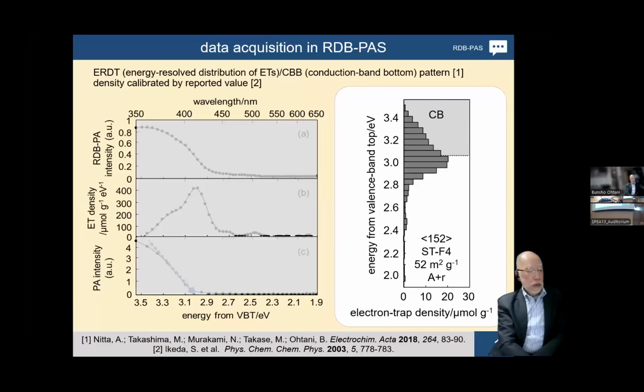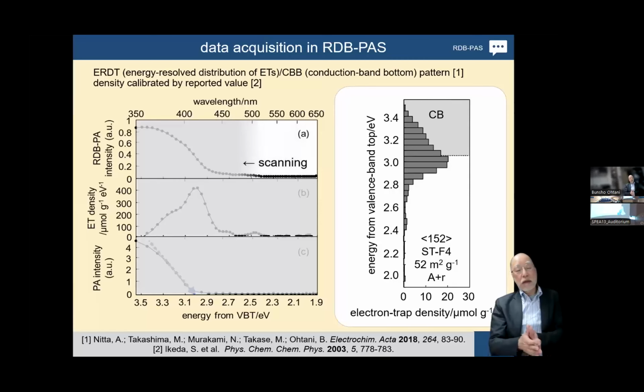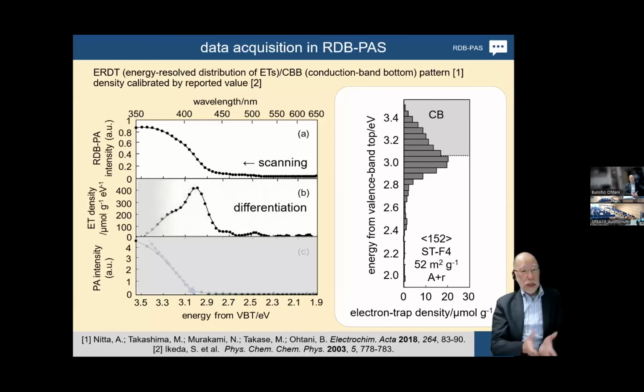The left top one is the scanning of excitation wavelengths from the longer wavelength side to the shorter. At 450 nanometers, the electron trap filling started and then filled up, and at about 350 nanometers it is almost saturated. By differentiation of this spectrum from the longer wavelength side, this is the energy-resolved distribution of electron traps in relative scale.